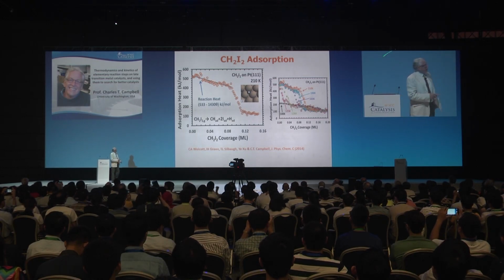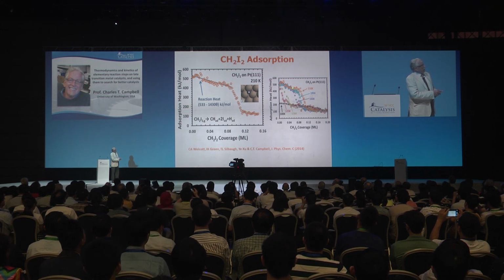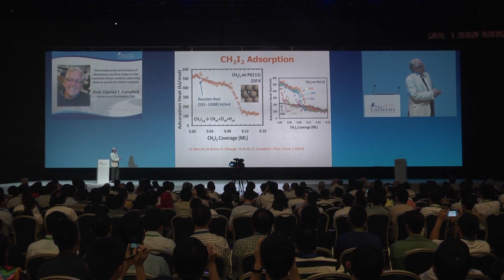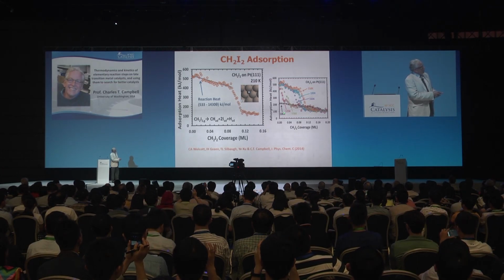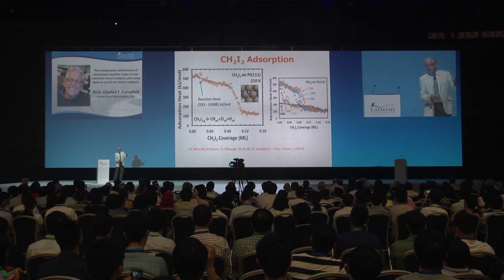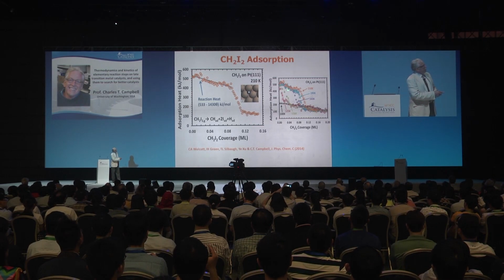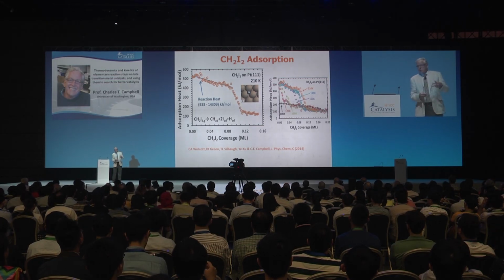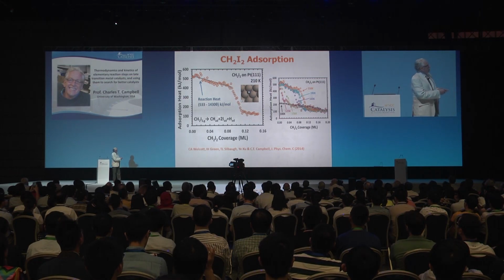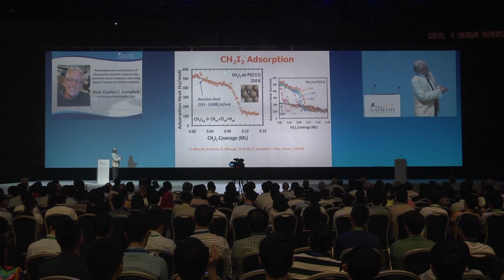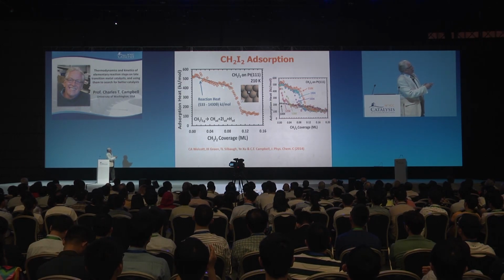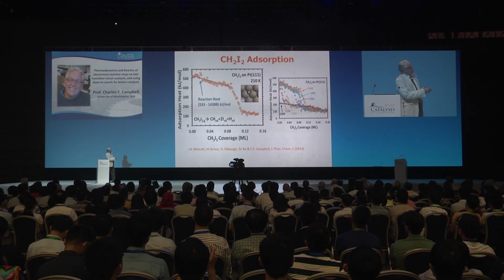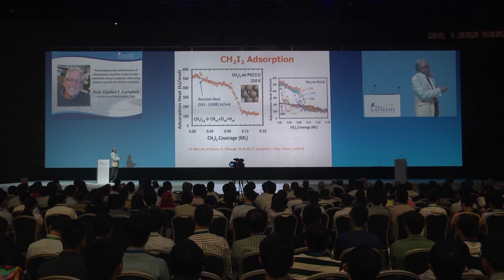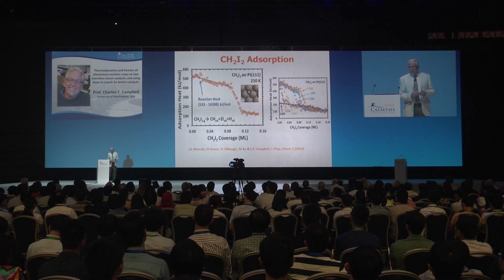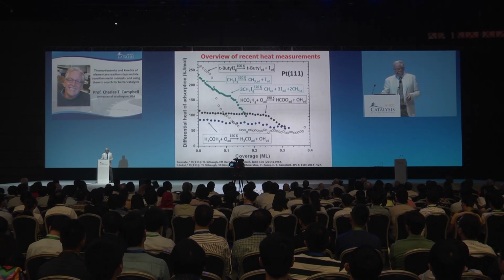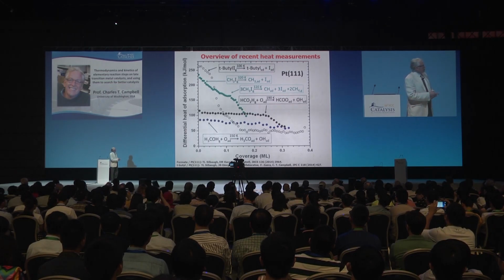I put this up to show the flexibility that we have with the calorimeter. These are measurements of the heat of adsorption of diiodomethane at different temperatures on platinum. At very low temperature, when you adsorb this molecule, the two iodine atoms cleave off and you make CH2 and two iodine atoms. Whereas if we go up to 210 Kelvin, two iodines and a hydrogen cleave off and we make a CH group on the surface. This top curve is blown up here, and you can extract from that the heat of reaction. Because we know the heat of formation of iodine atoms and hydrogen atoms from temperature-programmed desorption, we can get the heat of formation of the CH group on that surface.